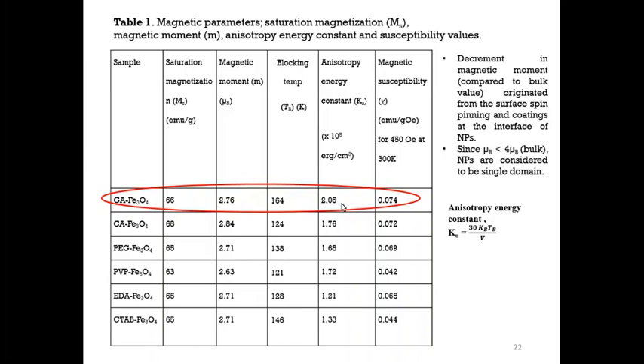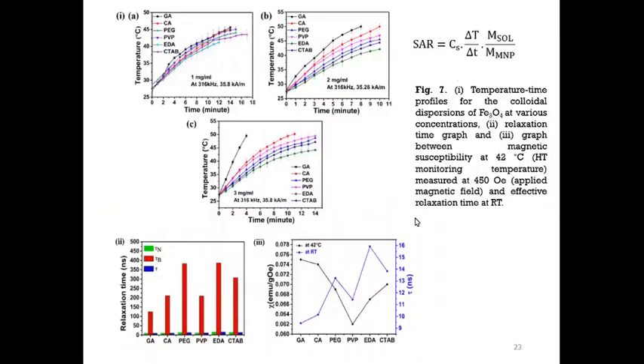So it possesses the higher magnetic susceptibility as well as the higher anisotropic energy. Yeah. So if we see the glutamic acid one, of course, you can see the leading one is the glutamic acid, which generates the higher temperature in very little time. Within 2 to 3 minutes, we can get it.